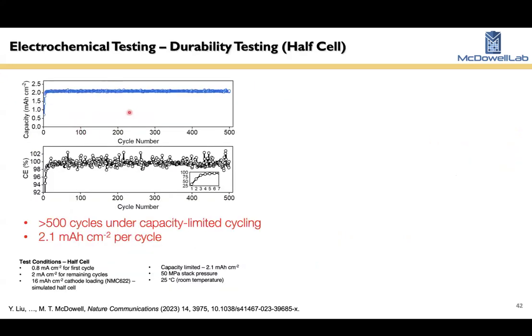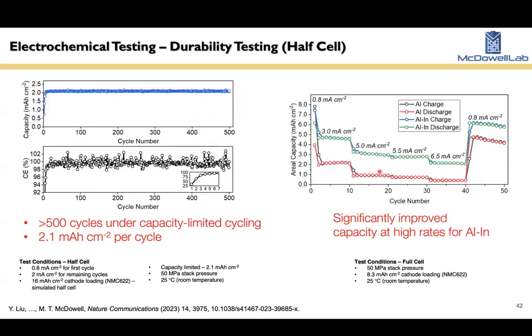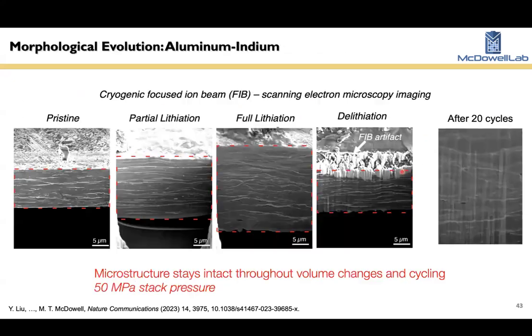We've seen very good durability on these materials at relatively high stack pressures in solid-state batteries. This is 500 cycles with controlled capacity cycling. We also see that this two-phase microstructure improves the rate capabilities quite a bit as well. We can get up to 6 or 7 milliamps per centimeter squared in a lab scale cell without short circuiting, and retain some of the capacity as well.